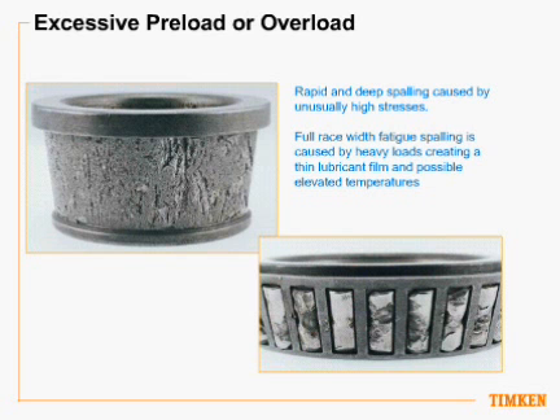You can see the rapid and deep spalling caused by unusually high stresses. When we say high stresses, we mean on the bearing components themselves. So the roller places stress on the cone and places stress on the cup. Normally for damage at this level, the temperature has been elevated and the surface has been softened due to that elevated temperature. Now, normally you can start annealing a cone at as low as 350 degrees, or a bearing component. So if the bearings get over 350 degrees, you can actually start to soften or reduce the temper in the steel.